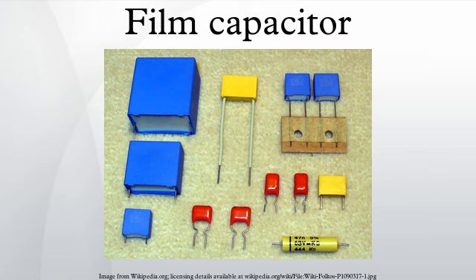In addition, PP film capacitors have the lowest dielectric absorption, which makes them suitable for applications such as VCO timing capacitors, sample and hold applications, and audio circuits. They are available for these precision applications in very narrow capacitance tolerances. The dissipation factor of PP film capacitors is smaller than that of other film capacitors. Due to the low and very stable dissipation factor over a wide temperature and frequency range, even at very high frequencies, and their high dielectric strength of 650 V/micrometer, PP film capacitors can be used in metallized and in